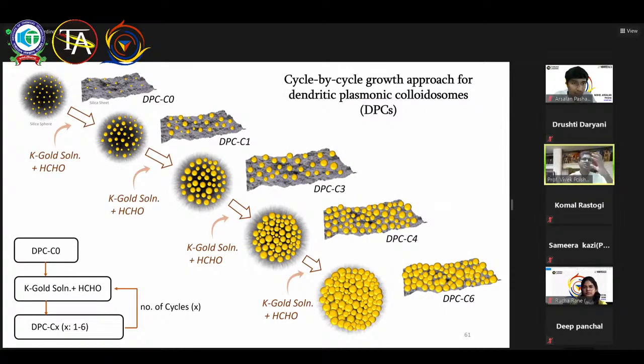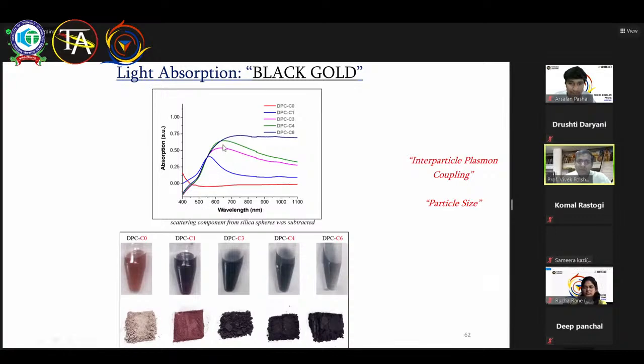We took these DFNS and then coated them with gold nanoparticles. And there we tuned the distances between the gold nanoparticles. We brought them together as close as possible so that the electron clouds of these gold nanoparticles start interacting and coupling with each other. And that allowed us to harvest the total solar energy. You can see now you can harvest the entire visible and near IR light using this black gold material.